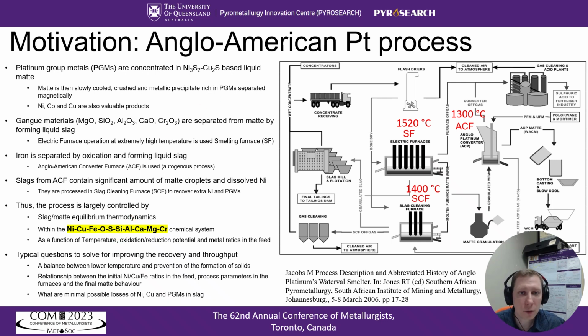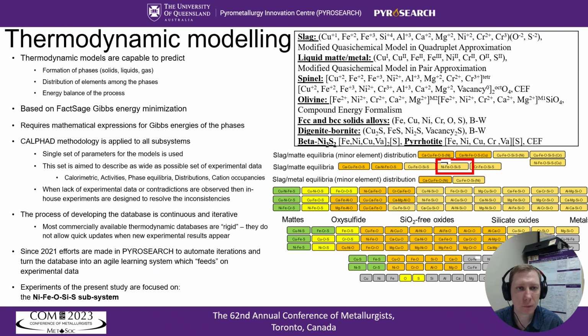The typical questions to improve the recovery and throughput involve maintaining the balance between temperature and formation of solids, relationship between the initial nickel to copper to iron ratio in the feed, process parameters, and final matte properties, and questions of minimizing the losses of nickel, copper, and PGMs into the slag. The purpose of thermodynamic calculations is to predict at least three things: the conditions of formation of phases, liquid or solid, the distribution of elements among those phases, and energy balance.